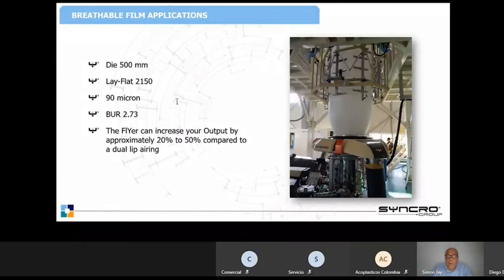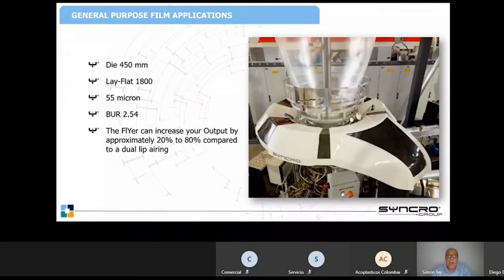For breathable film applications, a 500mm die, you can see the different characteristics there. Here you would expect to see a 20 to 50% increase. And for general purpose films, just taking a standard one of a 450mm die, 1800 lay flat, 55 micron. Here you can see anything between a 20 and an 80% increase in output.